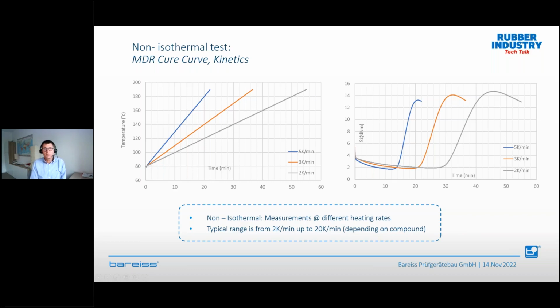And what you get is the answer here. It's S prime in dNm as a function of time. So what happened? The torque is decreasing, it's clear, because the temperature is increasing. And at a certain time or temperature, it starts curing and you get a curve like a cure curve. You can also calculate the minimum and the maximum. And this can be done again at different heating rates. The reason for this is,